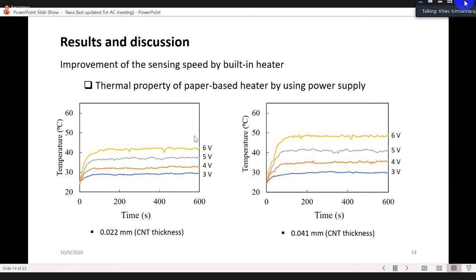This is the result of the thermal property of the paper-based heater utilizing a power supply. For the first one, I coated with 0.022 millimeter of CNT thickness. The temperature is around 28 degrees Celsius when we apply 3 volts. Then it can reach around 32 to 34 when I apply 4 volts, and then around 40 degrees Celsius when we apply 6 volts.